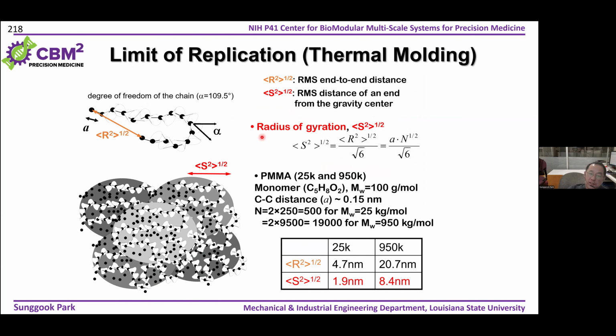Basically, this slide shows the smallest feature you can produce using thermal molding. This is the polymer chain, which is in an entangled state. If you calculate the radius of gyration, based on the end-to-end distance of a single chain, you can get it using this formula. If we apply it to PMMA with different molecular weights, 25K and 950K, you get a radius of gyration of around 2 nanometers and 8 nanometers respectively.